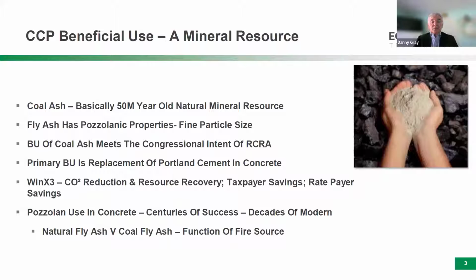Basically, under the rules, in terms of what is coal ash and how does it function within the recycling industry or within the mineral resource field, I refer to coal ash as basically 50 million year old dirt that happened to be with the organic matter that settled out 50 million years ago when the coal bogs were being formed. That mineral, which is the natural erosion soils of the time, ended up being nested in with the coal. And when you burn the coal, the mineral component does not combust, and it turns into either fly ash or bottom ash. But basically, the organic material is fired in the boilers, and it leaves the mineral component.